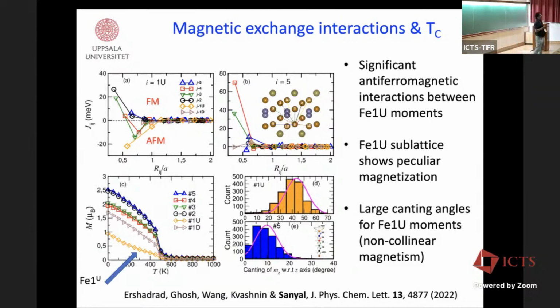So what does it tell us? It tells us that at low temperature, this system has a somewhat complicated magnetic structure. And it is very much dependent on the iron sublattice that we are talking about. The iron 1 sublattice is a very special case, where you have a large canting angle compared to the other sublattices.